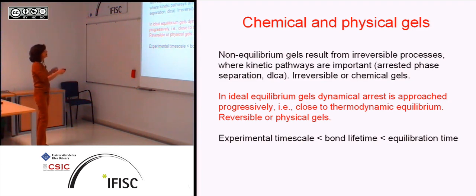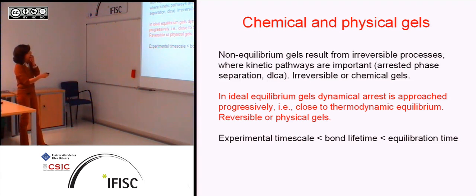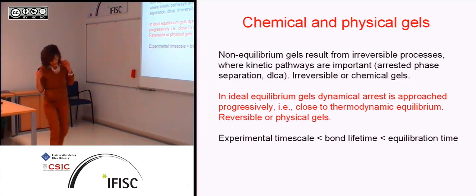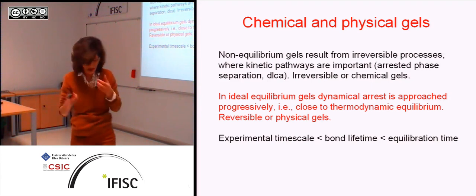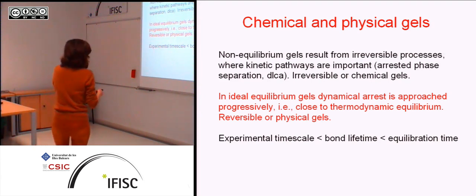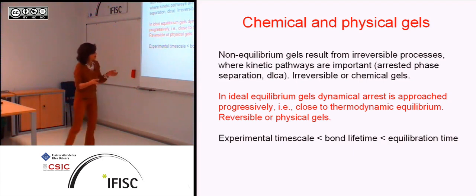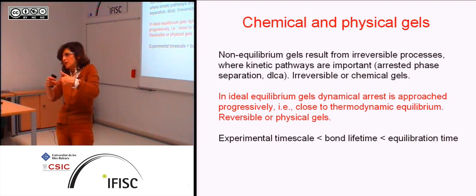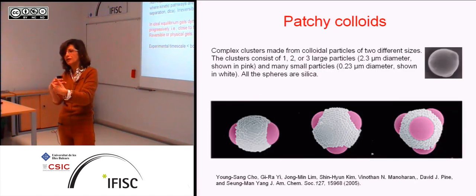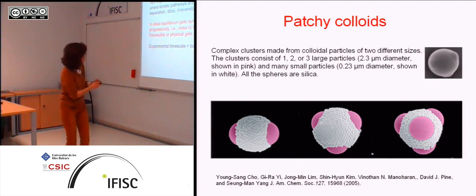This is the DLCA, but does it even make sense to consider equilibrium reversible gels? Well, basically we need some attraction for the bonding. And if you want to increase the bond lifetime, one thing you can do is to decrease the temperature. But you have to decrease the temperature without hitting Tc. So to be able to decrease the temperature in the one-phase region, you need to depress the critical temperature. Otherwise you hit the two-phase boundary line, okay?